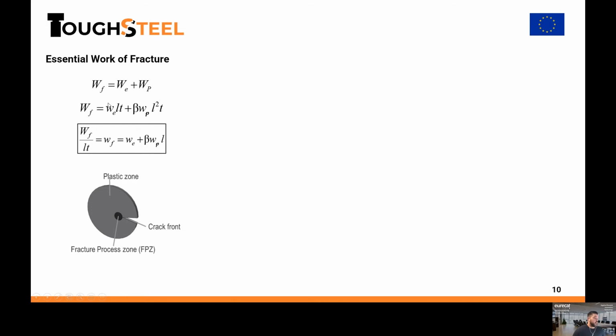Then, this specific essential work of fracture, which is developed in the fracture process zone, depends on the cross section. It occurs in the crack plane, while this outer plastic work depends on the volume. Okay, this plastic work surrounding the fracture process zone depends on the volume. Then if we normalize this equation, we have this final form, which is reminiscent of a straight line equation, no? When we have the ordinate, the independent term, and also the gradient multiplied by the variable. So how can we experimentally separate both terms?